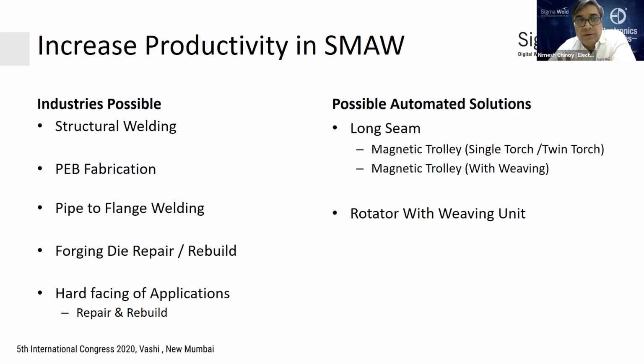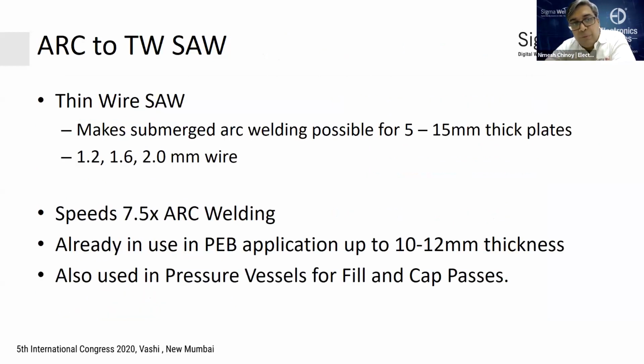If you wanted to increase productivity in arc welding, it is possible to do structural welding, PEB fabrication, pipe to flange, pipe to forging die repair, hard facing applications. You can automate them by moving to MIG-MAG or flux core wires using magnetic trolleys and with weaving units. If you move from arc welding to thin wire submerged arc, you could increase your productivity very fast. And this is very effective for low thickness, that is 5 to 15 millimeters, which is largely used in the infra sector for PEBs and girders and bridges, as Savant was sharing. So speeds up to 7.5 times arc welding can be increased.